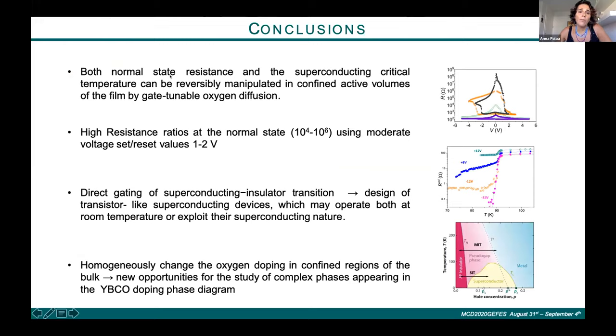I have shown that we have been able to modulate the normal state resistance and also manipulate the superconducting phase by inducing these voltage pulses. We have been able to modulate the resistance by these moderate voltage pulses, using very high resistance ratios. We have also been able to directly gate a bridge, which is a superconductor, and use a superconducting-insulating transition in a transistor-like configuration with a gate that controls if the system is superconducting or insulating.